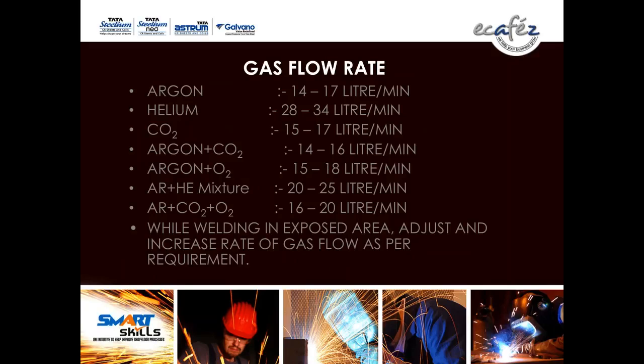Gas flow rate: check the gas flow rate. For argon or an argon-based mixture in the MIG process, it should be around 15 liters per minute. But if you go for helium, it should be double, because the density of helium is less in comparison to argon. So for argon, around 15 liters per minute should be used, but for helium, it should be minimum double because of the lower density of helium gas.